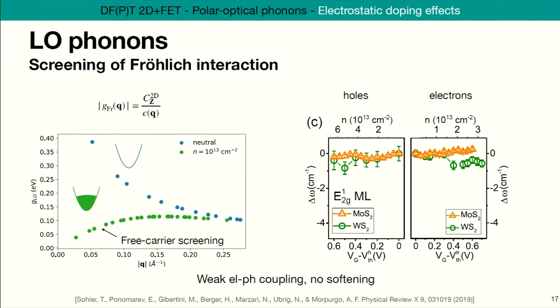It looks rather strong. But the issue here is that you're putting carriers into your system. You're doping your semiconductor, and you don't have a semiconductor anymore. You have a metal at some point. Once the Fermi level hits the band edge, you have a metal. And metals screen electric fields, which is the origin of all this coupling.